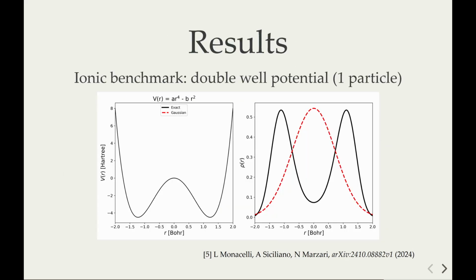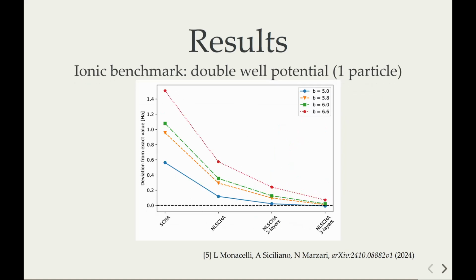Here is what happens in a double well potential. In red is the self-consistent harmonic theory, in black the exact solution. Now we apply one layer of transformation - gets a bit better. 2 layers, 3 layers, and as you can see, the more expressive the nonlinear transformation gets, the closer we get to the exact results. Here is how the energy changes with the number of layers we introduce, which converges exponentially. So we can go beyond Gaussian.